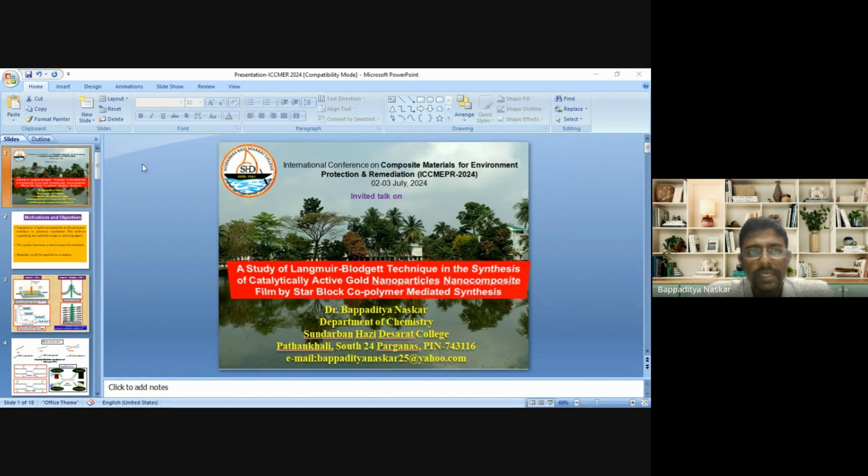And in the final phase, at around 12 or 14 millinewton per meter surface pressure, the PEO group has nearly penetrated into the water surface, and in this case, as the PEO and ethylenediamine are close together, they have more interaction with the water. So it looks like a brush conformation for T701, but for T90R4, it looks like a reverse umbrella position in the final stage.